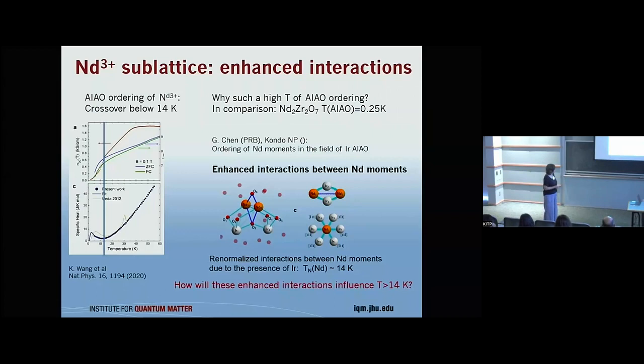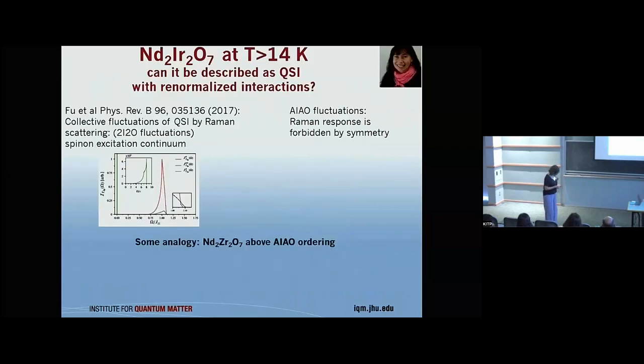An alternative way to look at it, which Natasha suggested, was to look at how the presence of extended orbitals of iridium enhances the interaction between neodymium moments. There are many pathways where the exchange interaction doesn't go from neodymium, oxygen, neodymium, but from neodymium, oxygen, iridium, and back to neodymium. And there are many of these pathways. So we thought that there could be enhanced interactions between neodymium atoms, and that leads to some special behavior of the system.